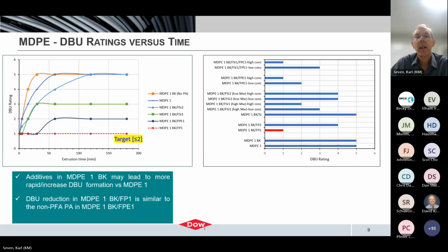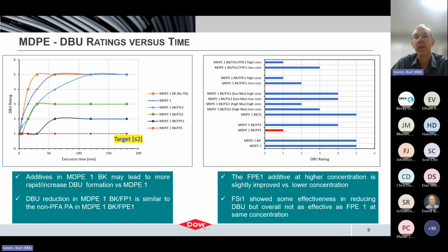So this graph on the right is basically a summary of all of the medium density compounds that were looked at. And one thing I'll point out is that we looked at the results for the polar polymer additive, which I mentioned, showing good performance. We looked at that at 2 different concentrations, and we did see a slight improvement in reduced die buildup at the higher concentration versus the lower concentration, showing basically a rating of a 1 versus a 2. As I mentioned, the functionalized silicone did show some effectiveness, but overall was not as effective as the polar polymer additive at the same concentration.